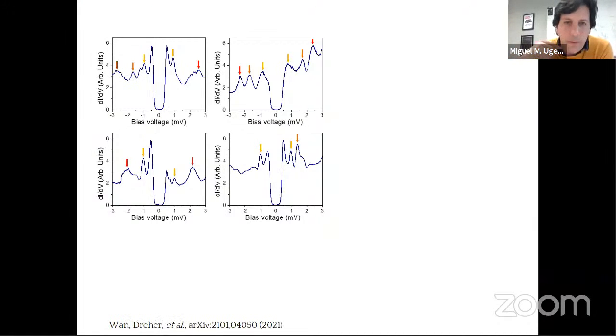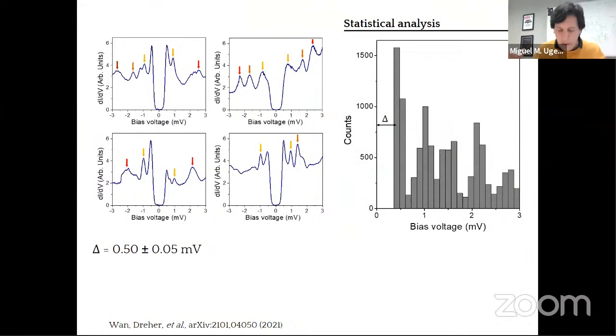In order to put some numbers and quantify the emergence of these satellite peaks, we have done some statistical analysis. We have taken thousands of curves in hundreds of different places. This is the resulting statistical analysis, a histogram for all of our curves, where you can see 5 different peaks.